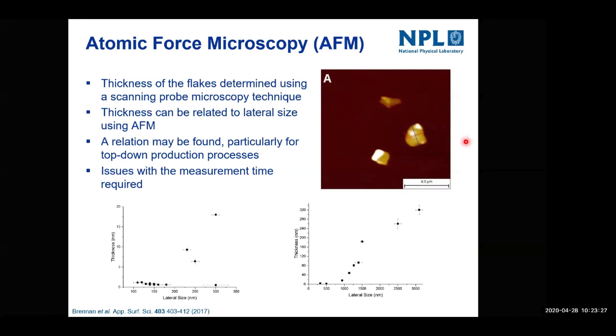We then want to look at the thickness. That's where atomic force microscopy comes in. Now, AFM is a scanning probe technique. So essentially, you're taking a tip that's got a nanoscale sharpness at the apex, and you're moving it along a surface to understand the topography. And you produce an image like this here, where the brighter areas are essentially higher. So you can see that there are three kinds of features there. By using this technique, we can determine lateral size like SEM, but also the thickness.